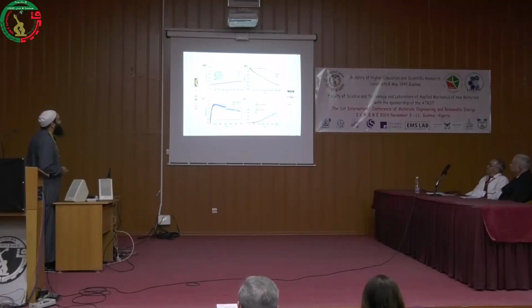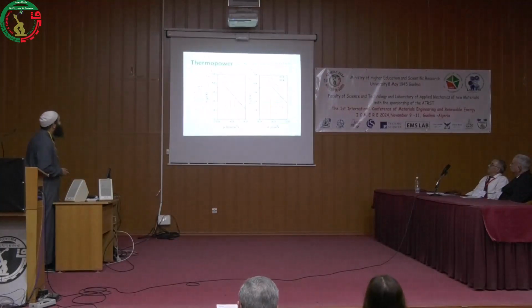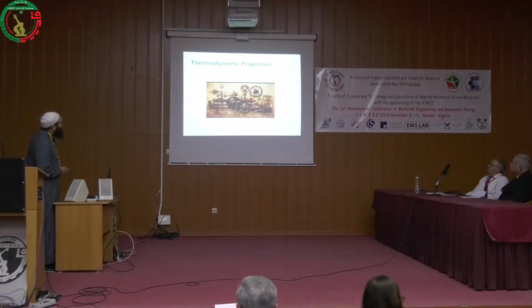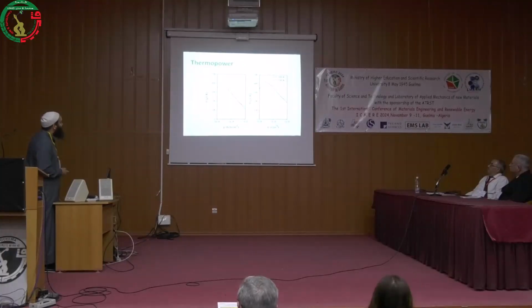The ZT that they found is very small, but as we saw in this picture, it can be improved. Here they found a Seebeck coefficient of around minus 250. And here we saw that we can reach till minus 400, so it's around two times. By including a good doping to this system, we expect that we can improve the efficiency of this material. And thank you very much for your attention.